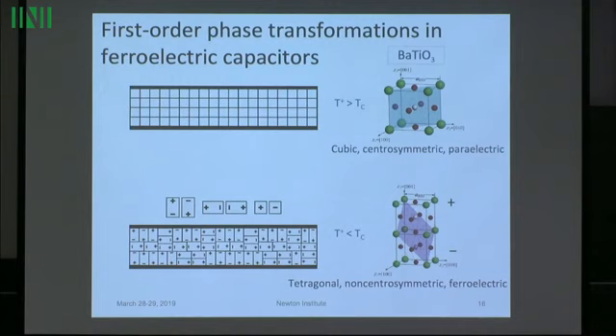But okay, so the idea is we use capacitance, and the main effect is we could be in this cubic phase, and we put it as the dielectric in between the plates of a capacitor. And then when we transform to the ferroelectric phase, we get these variants. This is a cubic to tetragonal phase transformation, so three variants. Like the magnetic case, there's also the plus or minus, so there's effectively six energy wells, and we discussed that in the other lecture.